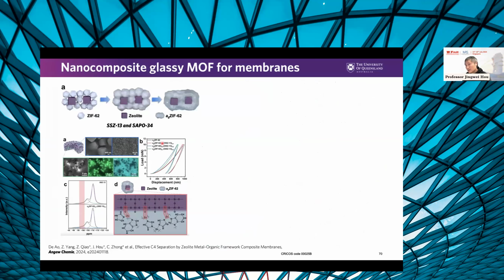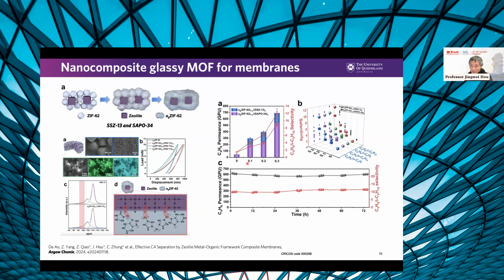The other thing is whether we can use MOF glass as a substrate for membrane making. Can we make mixed matrix membranes using MOF glass to replace the polymer? The answer is yes. We can choose almost endless options to make triple-M membranes using MOF glass. In this case, we demonstrated using traditional zeolite powder, a material that is difficult to make into a membrane composite with a polymer, with a ZIF glass. Because their interfacial compatibility is so good, we're not creating any additional defects. And surprisingly, you can see that by increasing the loading of the zeolite, we increase the permeance of C4H6 and also increase the selectivity for different chemicals. This is something we don't see very often in mixed matrix membranes, because typically you have to compromise between the permeance and the selectivity within the composite material.